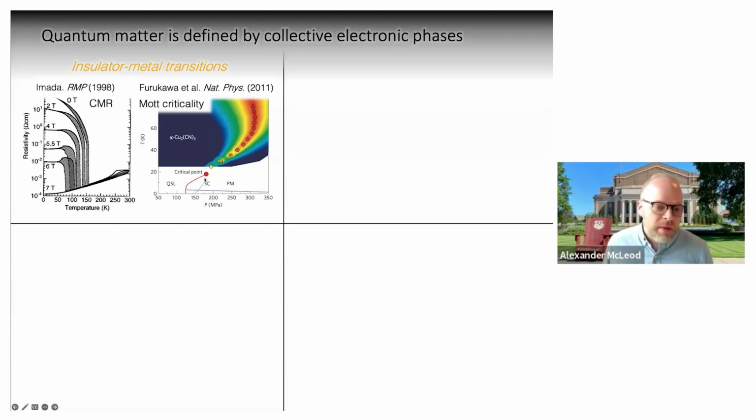So in our case here, this quantum material has a low temperature phase, which is a superconducting phase. It also has an insulating phase that can be triggered by the interaction between the electrons, and it also has a metallic phase. And shown here on the color scale is a derivative of the resistance with temperature. The funny thing to notice about this particular phase diagram is that it's really quite similar to other interacting systems, including the water phase diagram itself.